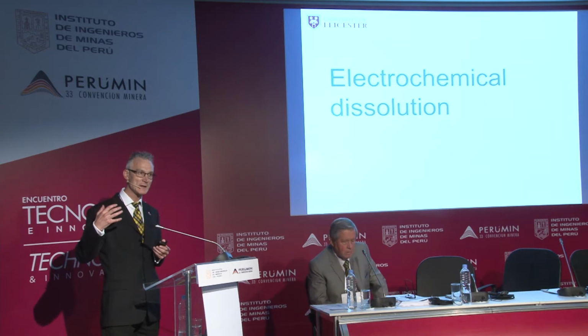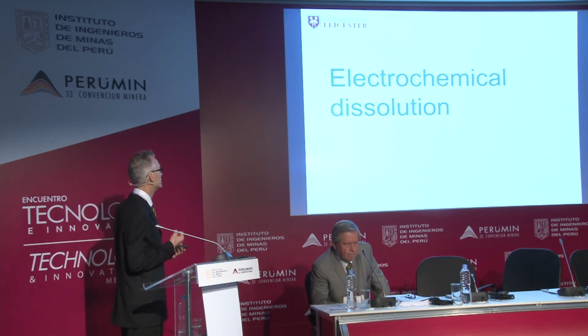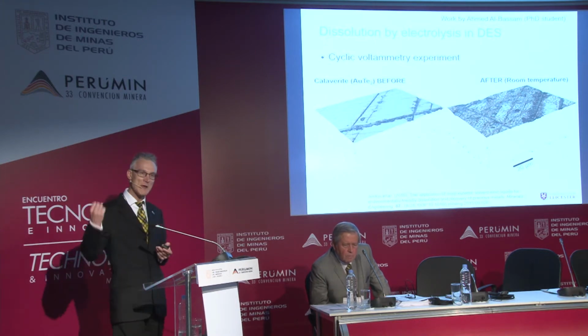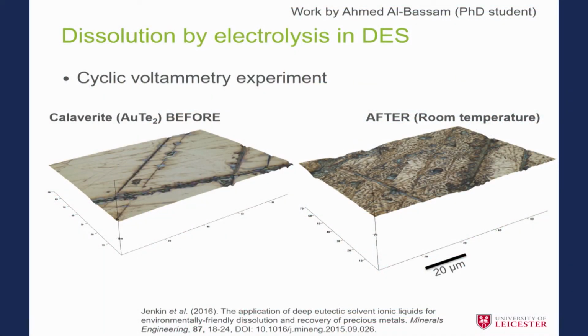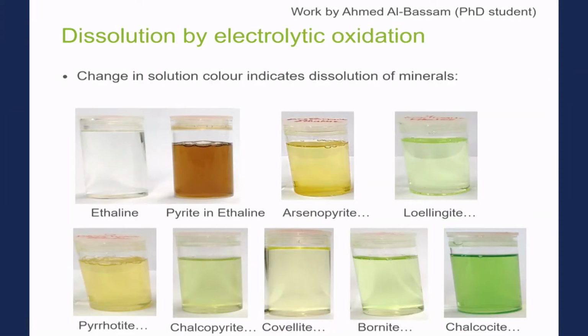But that brings me to the second mode of dissolution, electrochemical dissolution. We make the mineral an electrode, we add or subtract electrons, and we can cause it to dissolve. So calaverite, which didn't dissolve in iodine, you can see before and after it is dissolving. So we can deal with calaverite, and we can deal with all these refractory iron sulfide minerals. So here's our starting solution. We make our mineral an electrode. We suck out the electrons to oxidize it. And all these minerals, pyrite, arsenopyrite, lollingite, all these copper minerals can dissolve electrolytically.